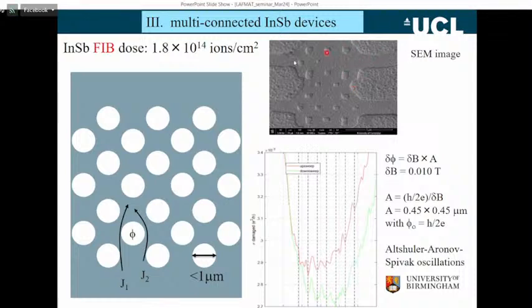Here is an SEM image. You can see the Hall bar. You can also see where we've etched the holes in here, and the holes are about 0.5 micron in diameter. And this is the experimental data here. So this is device conductance as a function of magnetic field. It's all happening at very, very low magnetic fields. This is device conductance as we sweep the field. This is an upsweep, the red curve, and the green is a downsweep. What I've actually done here is I've swept the field many, many times in each direction and just added the signal together to reduce the random noise level.